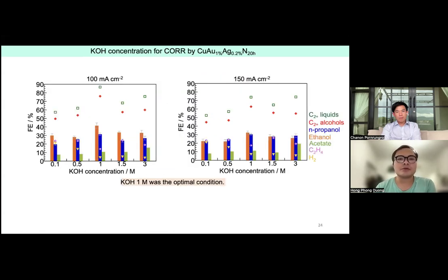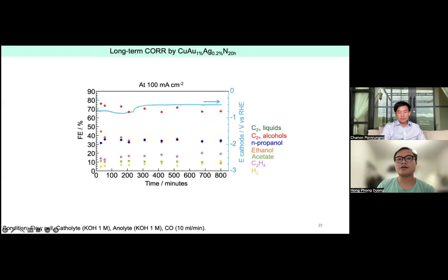And yes, again, we also tested the electrolyte concentration shown here. And the best one was with 1 mole of KOH, with 76% of C2+ alcohol shown here. And yeah, we performed the reactions for over 12 hours and found the system is somewhat stable under these conditions. Of course, you might have variations of the alcohols over time, but normally they are quite persistent.